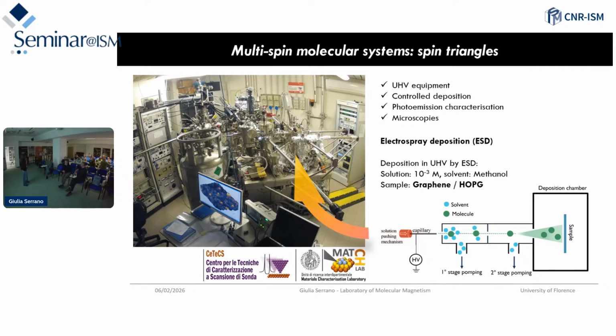So we have different preparation setups. In the main platform that I showed you, we basically study one single layer or a few layers, so as not to contaminate the systems too much. And also because we do XPS and we do STM, we don't need to measure the thickness. Then we have, of course, microbalances to check the rate, to have a feedback on the deposition. Our method is to deposit for as little time as possible, to decide on the STM basis which is our monolayer coverage. Then we get for that surface an intensity signal reference for the XPS side.